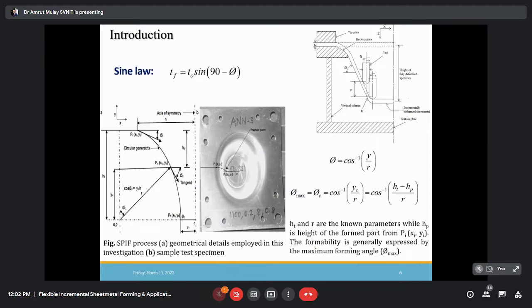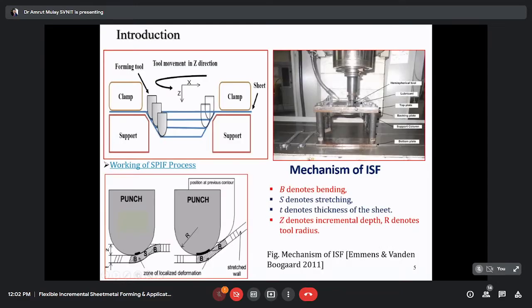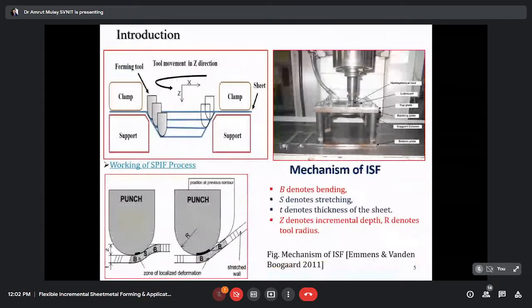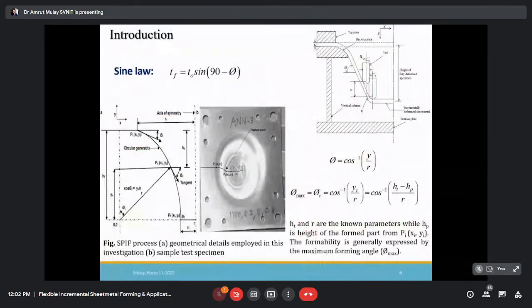So this is a rough indication, but one thing you should always remember: this estimation will give a clear or approximate idea only at the middle portion of the forming. What does it mean? I have shown you the previous figure. Now you know the stretching zone. This is bending, stretching, and bending. So only at the stretching zone is this particular relation valid. In initial bending and final bending, this relation is not valid. That you must understand.